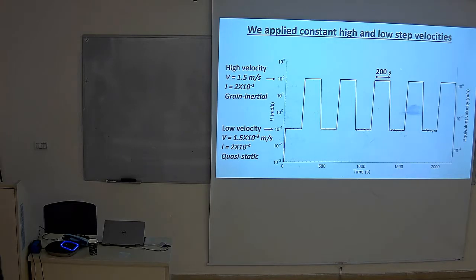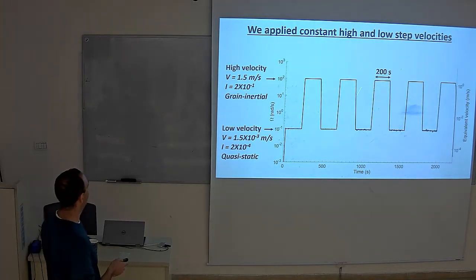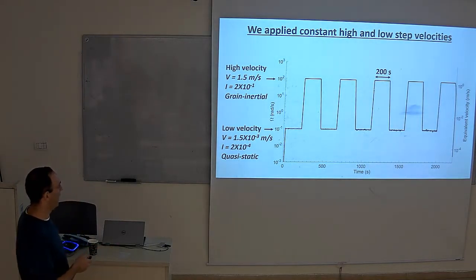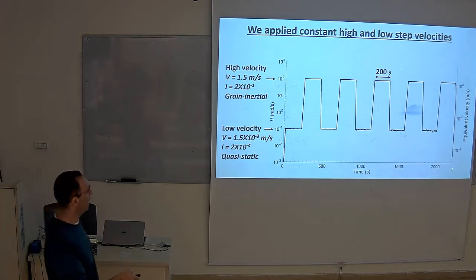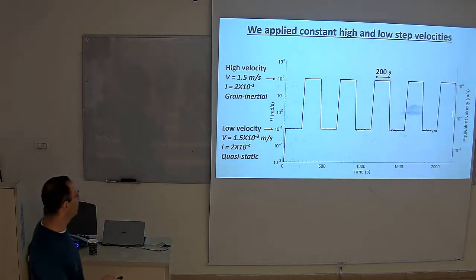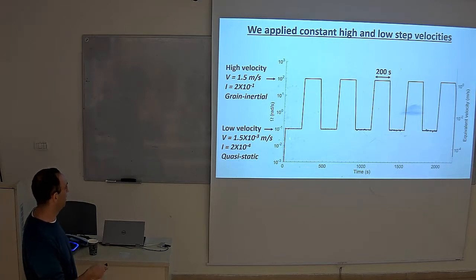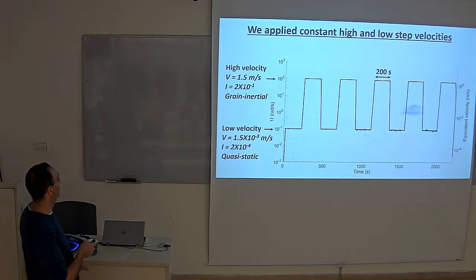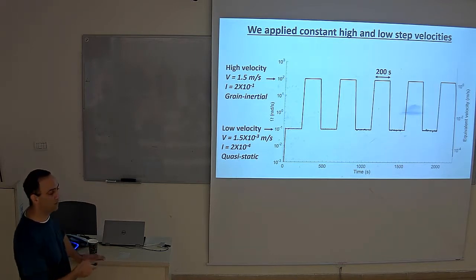So that's the procedure of an experiment, how we plan it and how it actually looks during the experiment. This is the angular velocity in radians per second. The other axis is the tangential velocity in meters per second, and this is the time along the experiment. So we accelerate from 0 to 1 millimeter per second, then jump to 1.5 meter per second, and so on. Each velocity step, at constant velocity, lasts 200 seconds. And according to calculation, the inertial number is 0.2 for the high velocity, which means that we should be in the inertial regime, and for the low velocity it is 2 × 10⁻⁴, which means that we should be in the quasi-static regime. So we're supposed to see it in our dilation measurements.